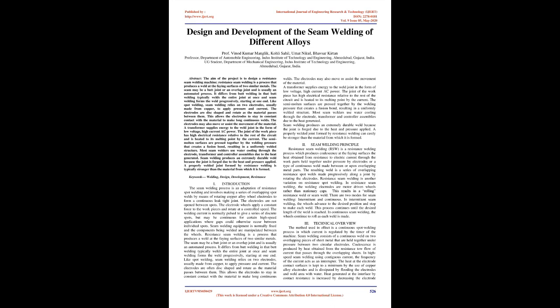The joint of the workpiece has high electrical resistance relative to the rest of the circuit and is heated to its melting point by the current. The semi-molten surfaces are pressed together by the welding pressure that creates a fusion bond, resulting in a uniformly welded structure. Most seam welders use water cooling through the electrode, transformer, and controller assemblies due to the heat generated. Seam welding produces an extremely durable weld because the joint is forged due to the heat and pressure applied. A properly welded joint formed by resistance welding is typically stronger than the material from which it is formed. Keywords: welding, design, development, resistance.